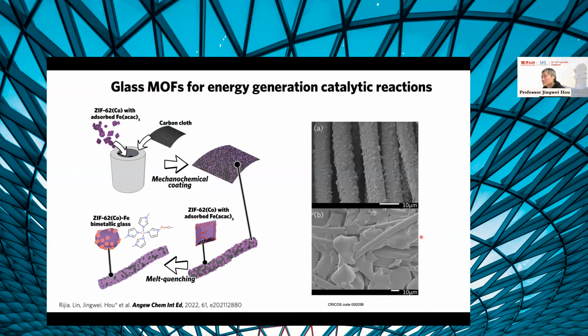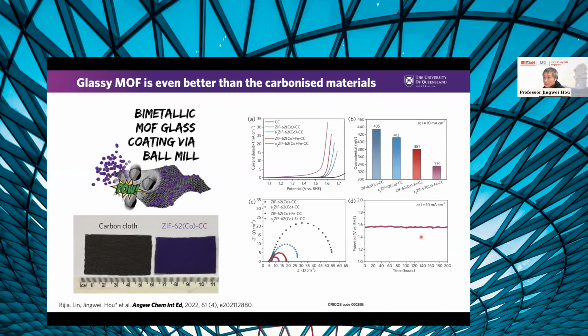So we just demonstrate this can be used for, say, an electrode, right? In this case, we put a cobalt-based glass together with iron, and we just coated on the top of carbon cloth, which is quite inert, quite difficult to coat. But in this case, we use ball milling to coat the MOF glass onto the carbon cloth. Then we melt the MOF glass to get an electrocatalytic reactive electrode. So that's a long name.